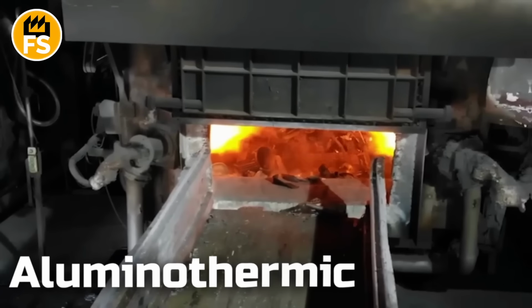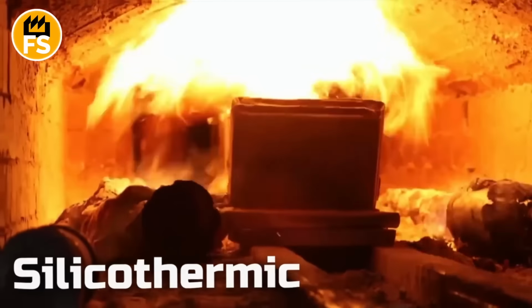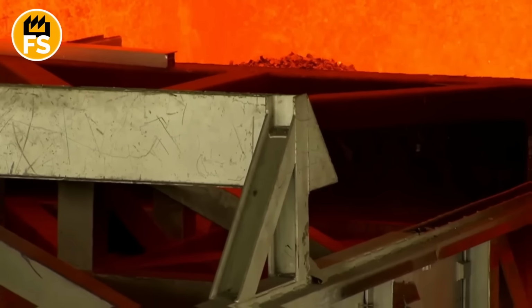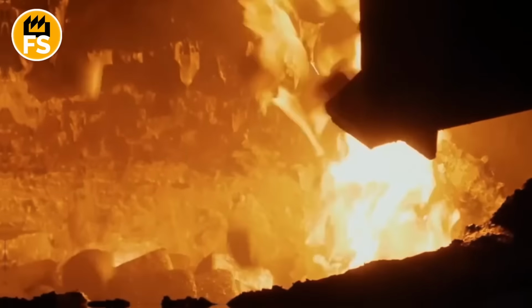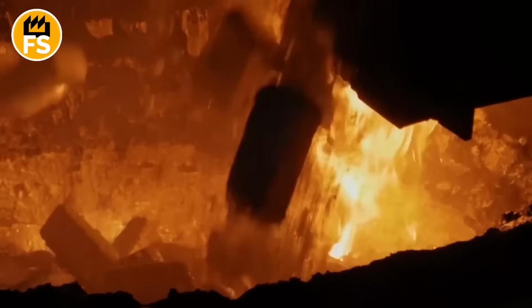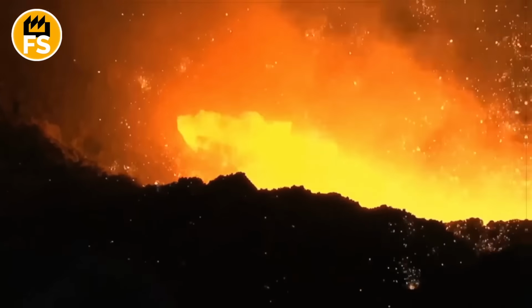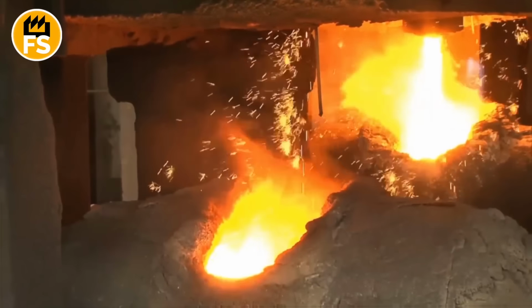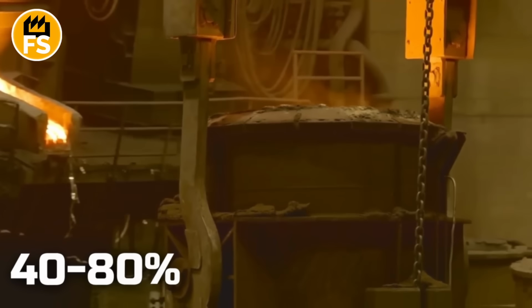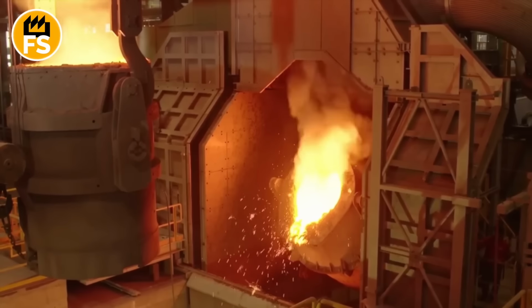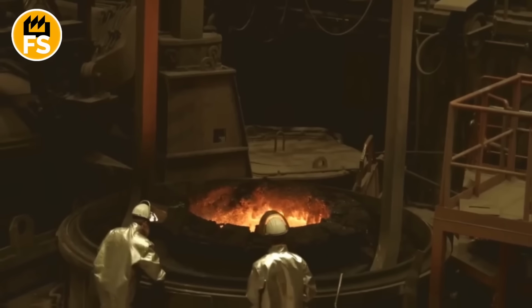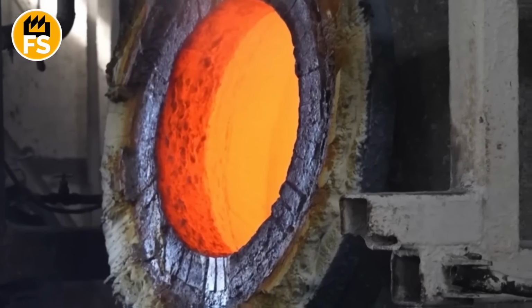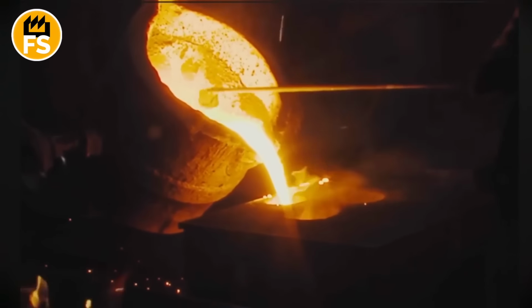During aluminothermic or silicothermic reduction, the reaction proceeds extremely rapidly and releases a significant amount of heat. Vanadium oxides surrender their oxygen to the reducing agent, while pure vanadium transitions into a molten state and immediately dissolves in the iron. The result is liquid ferrovanadium with a specified metal content, typically ranging from 40 to 80% vanadium, depending on customer requirements. After the reaction completes, the melt is held to stabilize its composition, then poured into molds.